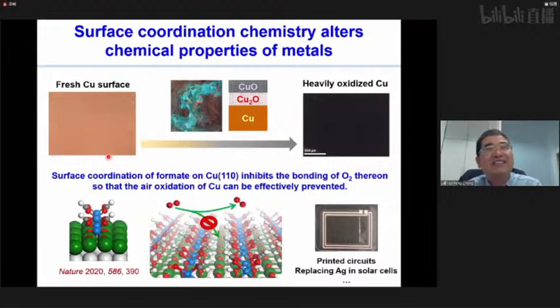However, after years of study, we found that if we treat the surface of copper with formate, those formates can form a really robust passivation layer, because the formates bind to the copper surface, particularly on the copper (1,1,0) surface. Basically, this passivation layer can prevent the chemical absorption of oxygen, which means that oxygen won't be activated on the surface for oxide formation. So with this understanding, we can try to use copper to replace silver, for example, for printing electronic circuits, and also replacing the silver in solar cells. So we are still working on the technology development for this field.